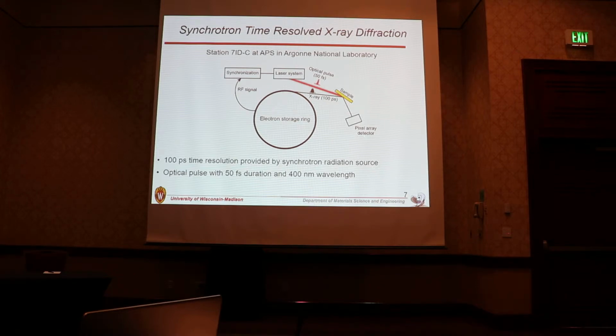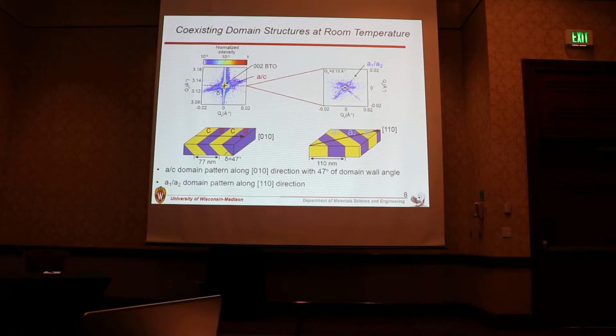We use a two-dimensional pixel array detector to collect the X-ray diffraction. We use a 50 femtosecond duration optical pulse with a 400 nanometer wavelength to excite charge carriers in the barium titanate. So first, we have built the reciprocal space map for this system to study the domain patterns.